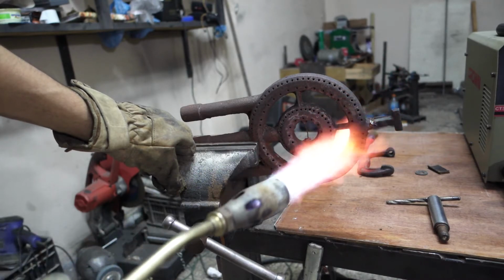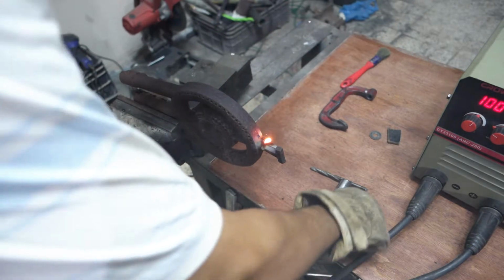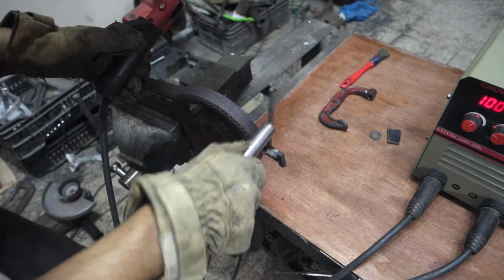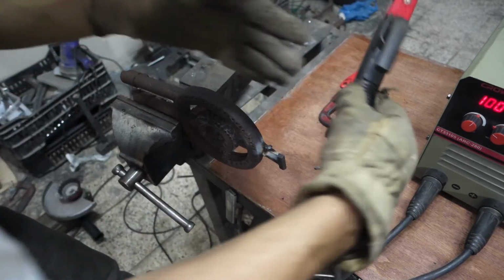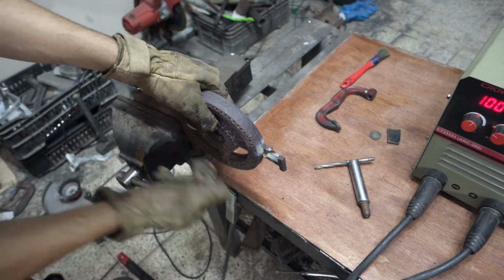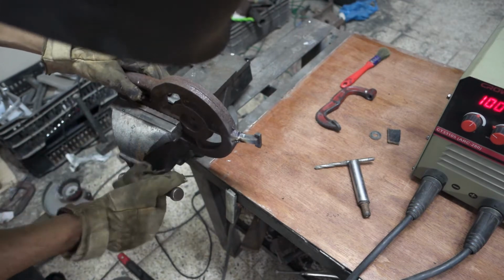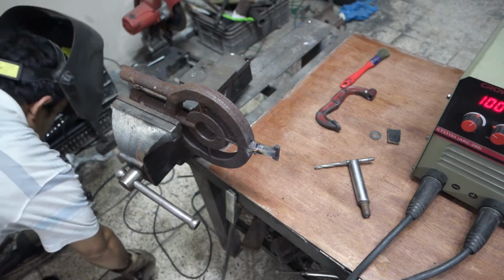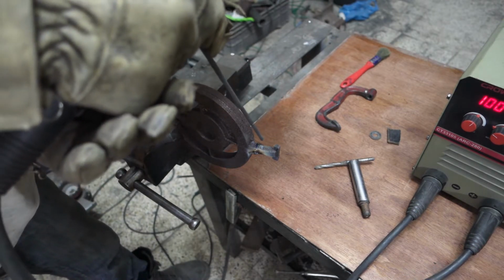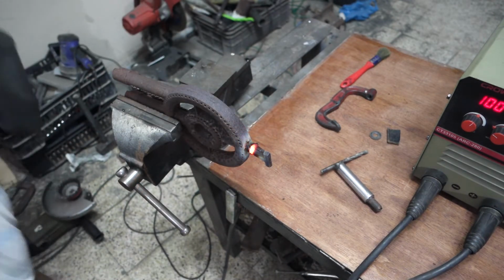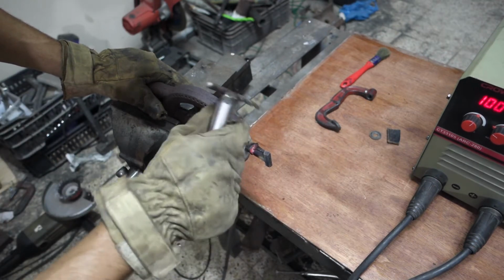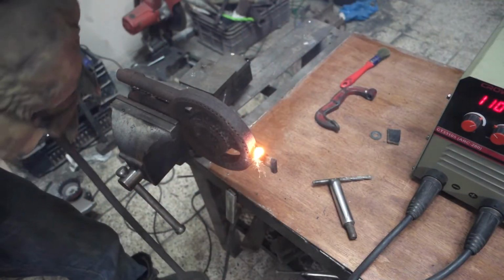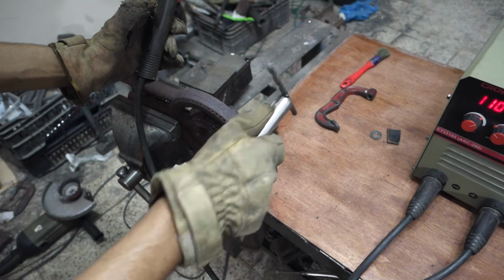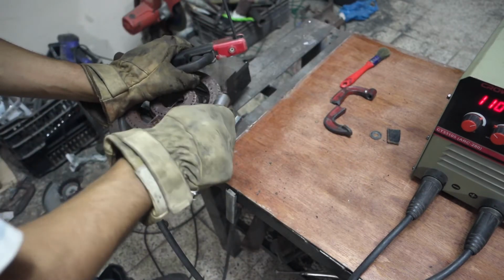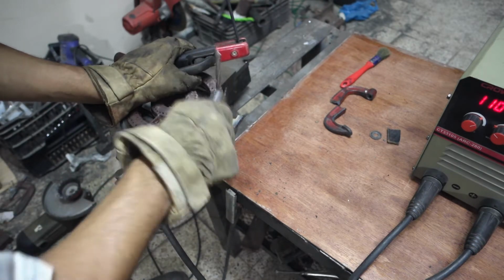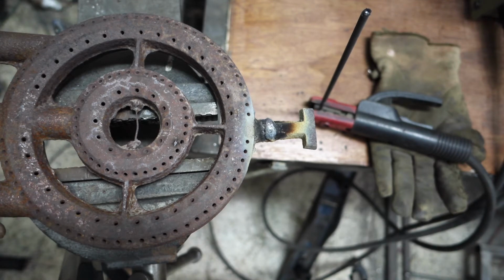I am welding at 100 amps, and I will not show you that because it is just a white light and you can't see anything. And I weld a bit and stop to hammer on the weld bead so it expands and does not pull the cast iron, to avoid cracks. I flip the piece and do the same so I don't put excessive heat on the same place. And I let it cool slowly, and you can even bury it in sand to hold the heat longer.